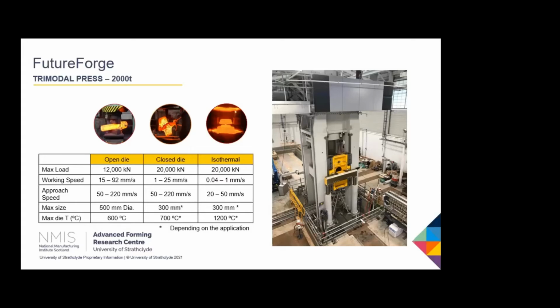For the open die, maximum temperature is about 600 degrees. For closed die, we can get up to a die temperature of about 700 degrees. The isothermal, we can guarantee 1200 degrees, but we're obviously going to be working with tool material specialists, and our aim is to get this up to 1300 degrees C eventually. The problem is that materials of this size and temperature capability are really expensive.